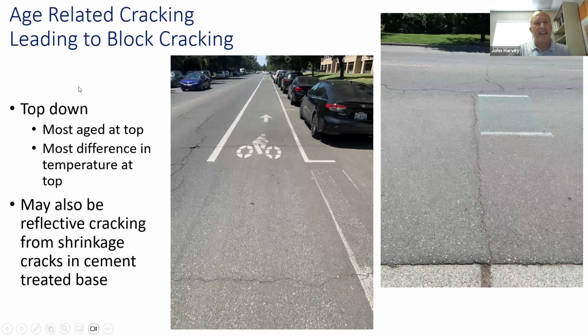Okay, so age-related cracking leads to top-down cracks. It cracks first in the transverse direction, then typically it will crack again in the transverse direction, almost halfway between the previous cracks. Here we can see those transverse cracks in my left-hand photo here. Got a little fatigue going on over here. And then eventually the shortest direction is longitudinal. So if we crack it a couple times transversely across the road, eventually the next time it cracks will be longitudinal, and what we've created is block cracking, and that's where block cracking comes from.